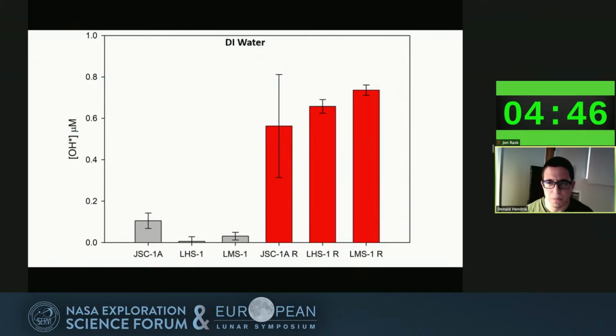There was the other paper that John also talked about, Wallace et al. 2010, where they tested the reactivity of various Apollo samples and compared that to fine-grained JSC1A, and they were able to see a huge increase in reactivity compared to the fine-grained JSC1A. They were also able to strongly correlate the reactivity with the maturity, or pretty much the amount of metallic iron that was present. So the advantage of this is that we can make these samples in the lab versus having to actually get pristine lunar regolith.